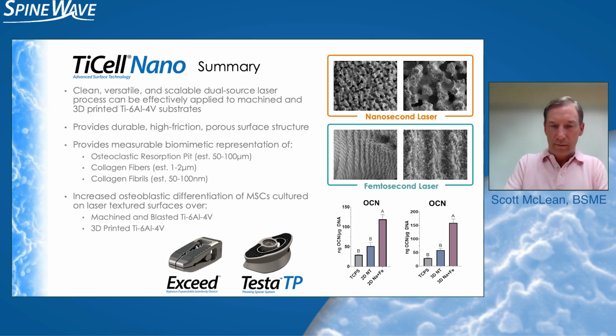So in summary, the dual laser process that SpineWave has developed is a clean, versatile, and scalable process. It can be effectively applied to both machined and 3D printed substrates. It provides a durable, high friction porous structure on its surface. It aims to combat implant migration and retropulsion. It also provides measurable biomimetic representation of the size or diameter of an osteoclastic resorption pit, the size of the collagen fibers present at the base of the osteoclastic pit, and the size of the collagen fibrils that those fibers are composed of.